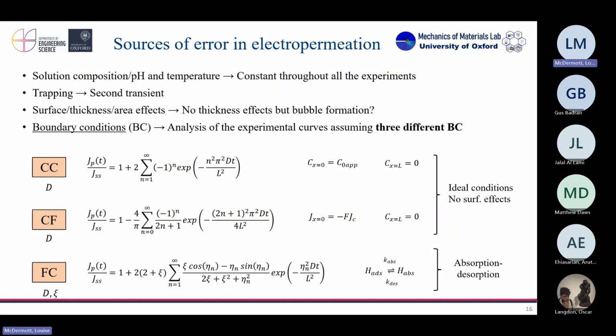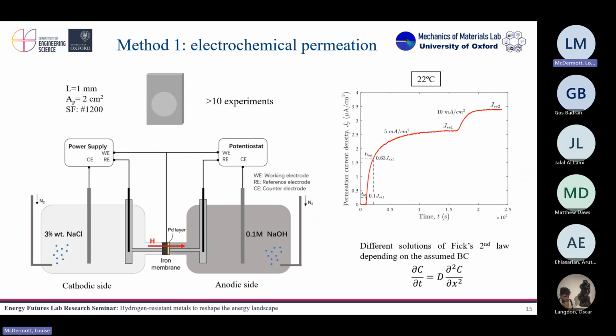Finally, we also have this trapping phenomenon that I told you about before. That's maybe a bit harder to understand, but imagine a material that has a lot of defects, hydrogen traps. At the beginning, when I start the experiment, that material doesn't have any hydrogen. So before I start seeing anything rise, and even during the transient, all those defects are going to be trying to capture hydrogen while hydrogen is flowing to the other side. So that's going to affect my results. That's what I call the trapping effect. But those defects are more or less filled with hydrogen during the first transient. So in the second transient, those effects are minimized, because most of the traps are already filled with hydrogen. That's what I did in this case: 2 permeation transients. So in the second transient, that trapping effect should be negligible.